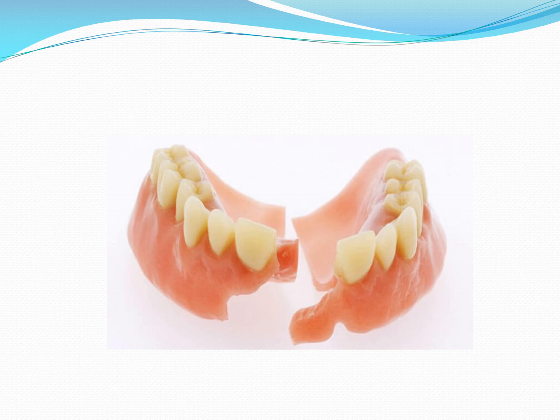The denture is separated from the cast and 2 to 3 millimeters of acrylic is removed from the fractured site. A wide bevel is created on either side of the fracture line. After applying separating media, the denture is replaced back on the cast. This is how we do a repair in the lab or even in the clinic.